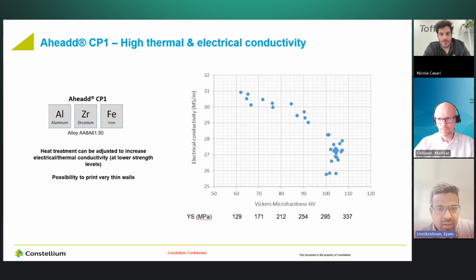This is an interesting property of Aheadd CP1, where based on the component design or property requirement, we can fine-tune the heat treatment. As I explained earlier, in the as-built situation, the alloy is very soft, only 130 MPa. In the peak age, it's around 300 MPa. So there is a good amount of bandwidth where we can fine-tune the properties and create a good trade-off between electrical conductivity and yield strength. This will be really helpful to mimic different types of alloys, or if you want to maximize the electrical or thermal conductivity for thermal management applications. This alloy brings a flexibility in terms of applications.